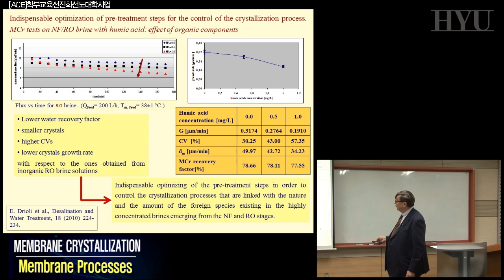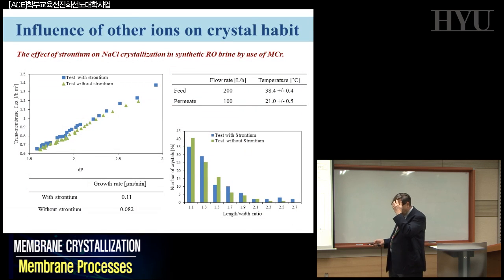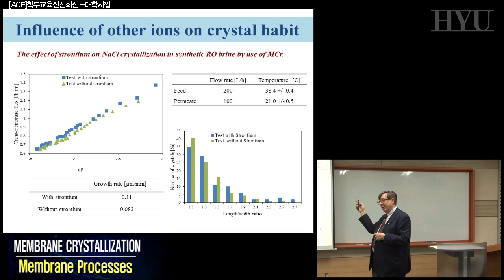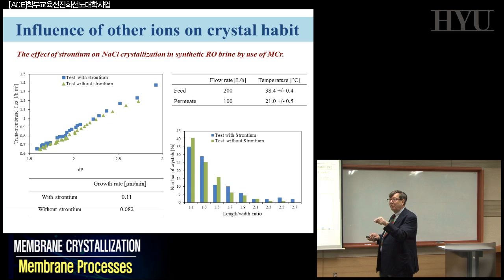crystals from your system. The other effect I was mentioning is the fact that even if you do very well, you separate calcium, for example, but it's very difficult to separate, for example, strontium, which is normally present in very low amounts. I think it is a few percent, so you don't take too much care. When you buy, or you go in your lab and you have, for example, magnesium sulfate, high quality, check carefully the composition of what you have been buying. You will realize they give you already a few percent of strontium; it is always present, because it is very difficult to separate, and so you are used to working with it.